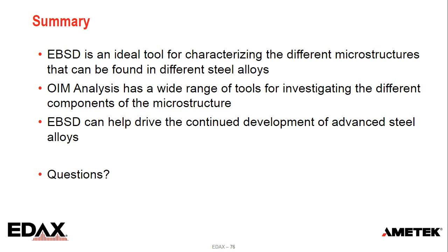There's a question here. It says, I had problems detecting retained austenite, and we tried transmission EBSD or TKD, which yields much better results. Yeah, and I had mentioned transmission EBSD. That's an approach where we use a thin foil and we look at the sample in transmission rather than reflection. Because of that, our interaction volume is minimized and we can get much better spatial resolution. Exactly. You can certainly improve spatial resolution that way.